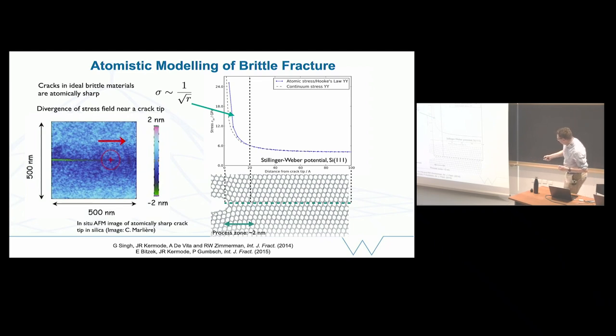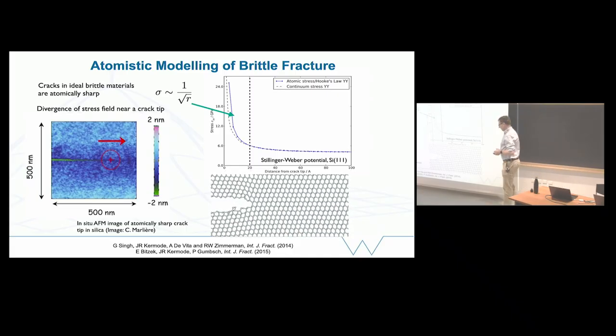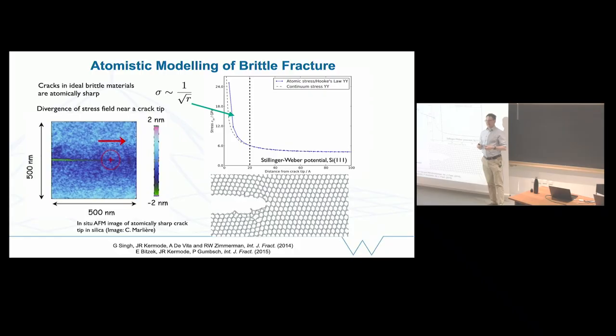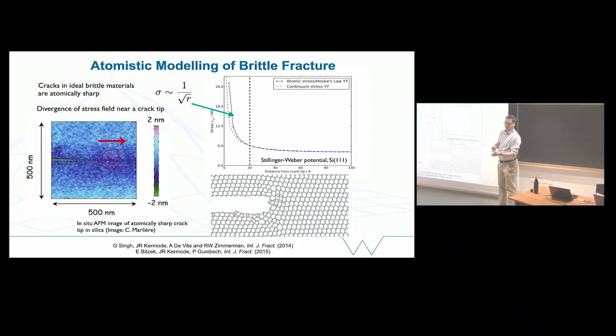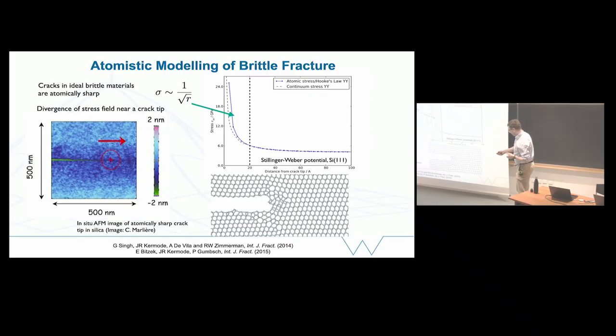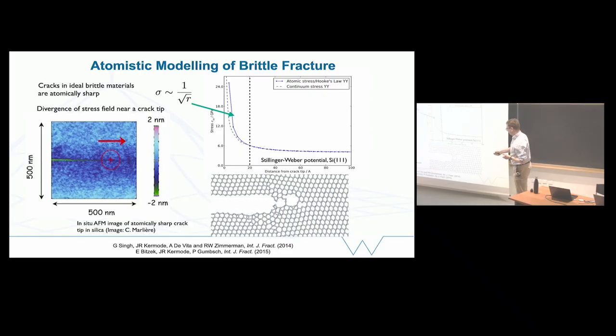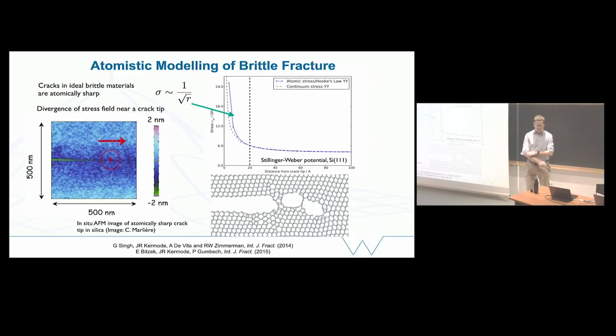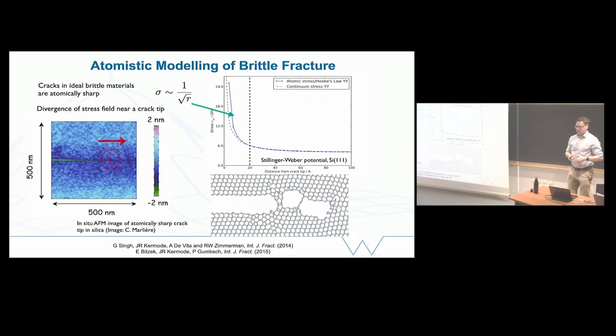Anywhere outside of here, everything is matching well, but in here, if I look at the dynamics, things go completely wrong with a simple potential because it's not sophisticated enough to break chemical bonds. You tend to overestimate how hard you need to pull. You put in far too much energy, and you get a big mess here. We're getting emission of dislocations, plasticity, the crack is arresting. It doesn't look like what we see in an experiment, where it's completely flat and completely smooth. So this is an example of somewhere where traditional interatomic potentials are not really sufficient.